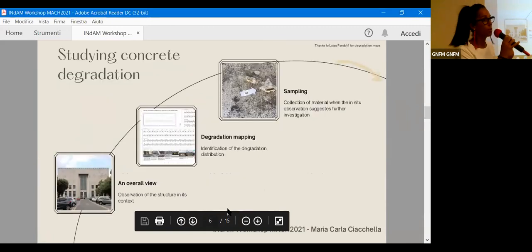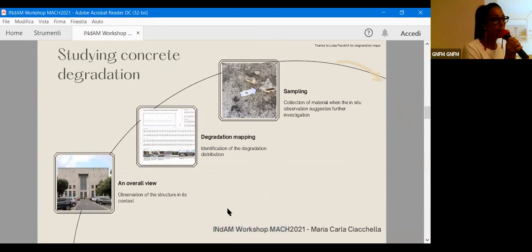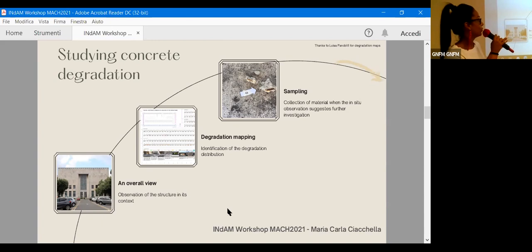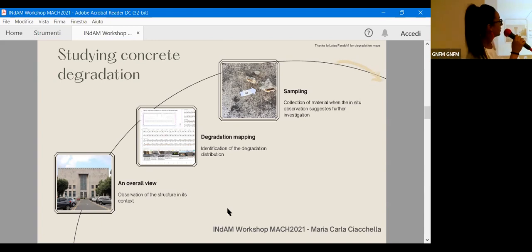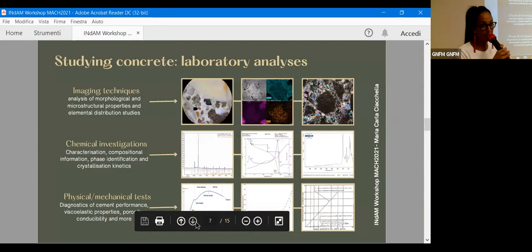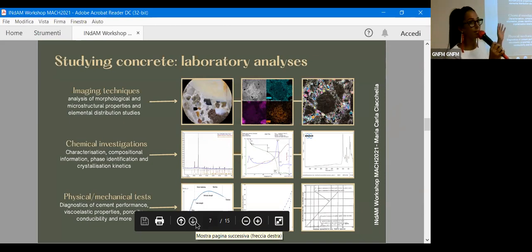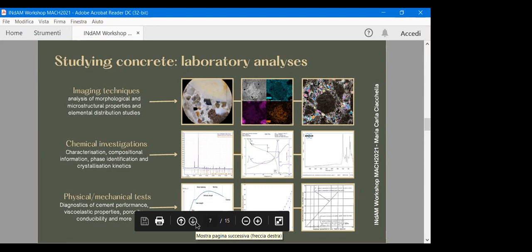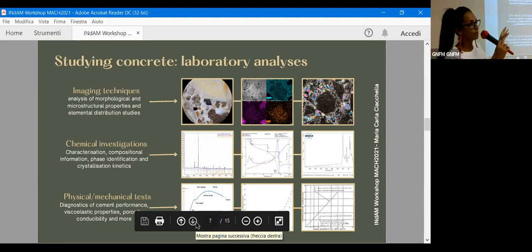I want to show you our workflow when we face a conservative problem. First of all, we have to observe the structure in its context, from a macro to a micro scale, trying to have an overall view of the structure. Then we pass to identification of the distribution of these phenomena. And then, only if the in situ observation suggests further investigation, we will sample. After sampling, of course, we pass to laboratory analysis. Here I try to simplify it in three main groups. First of all, the imaging techniques. Here you can see examples of microscopic pictures and mapping by using electron microscopy. We usually use imaging techniques for the analysis of morphological and microstructural properties.